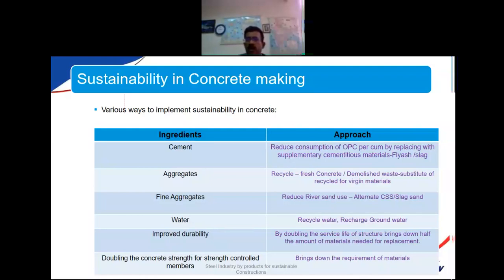Aggregates also, we can use recycled aggregates from the demolition of old buildings. That's one aspect. Second is that we can make slag aggregates, copper slag aggregates, fly ash based aggregates and all. So using these materials, the replacement can be up to 25 to 50% or 100% based on the concrete grade. For lean concrete, we can go up to 100%. So we can replace the virgin material using this construction demolition waste and also the slag industry byproducts.